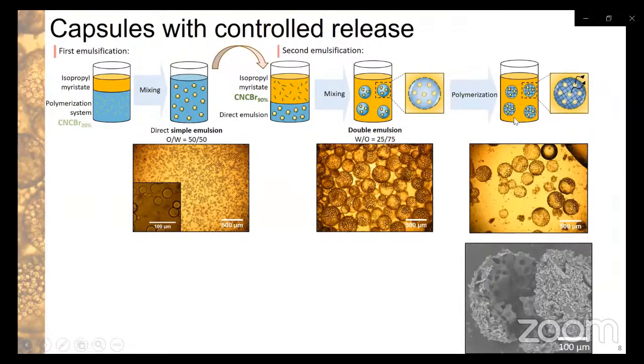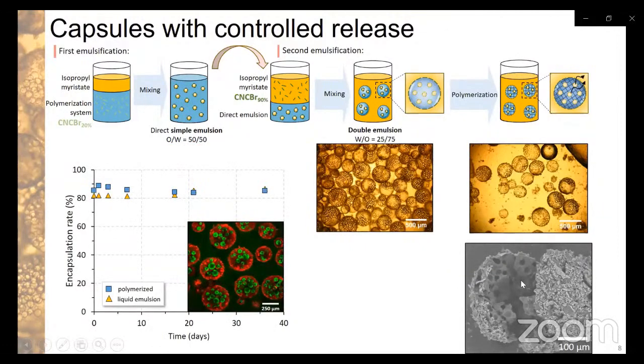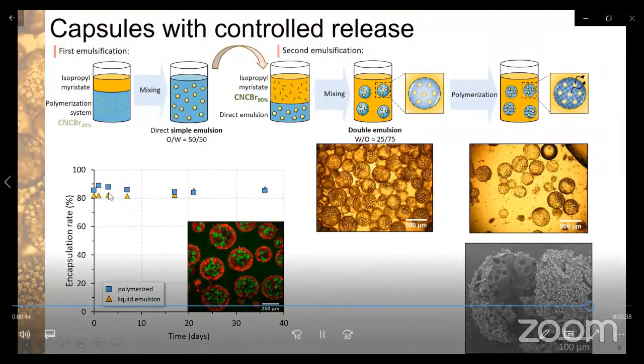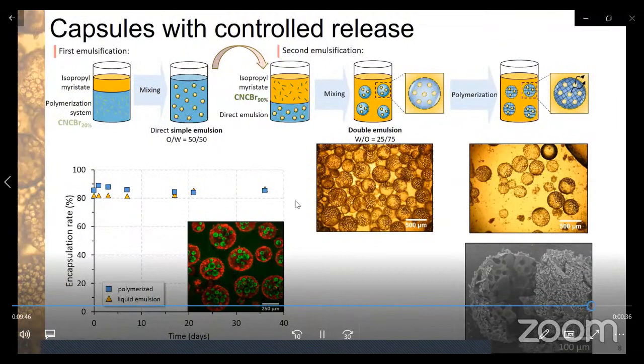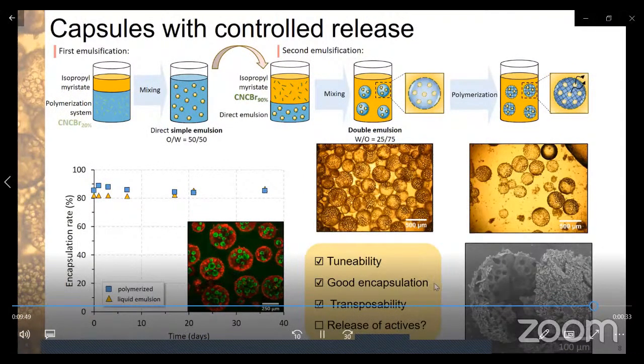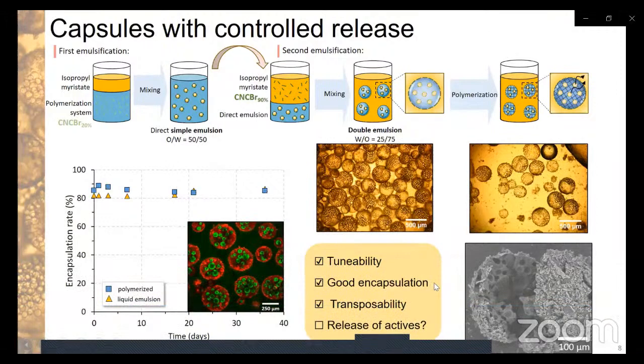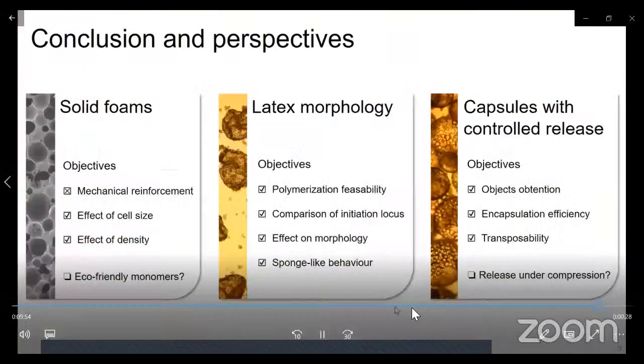We were able to polymerize it. You can see here that we have the polymerized beads with the imprints inside of the inner droplets. And this system was shown to be efficient as an encapsulation vessel for both hydrophobic and hydrophilic types, above 80%. More than that, we have something that is tunable with a good encapsulation efficiency, which is transposable to other polymerization systems. So as a conclusion, we did obtain 3 types of different materials.